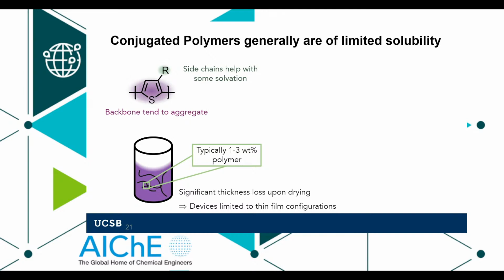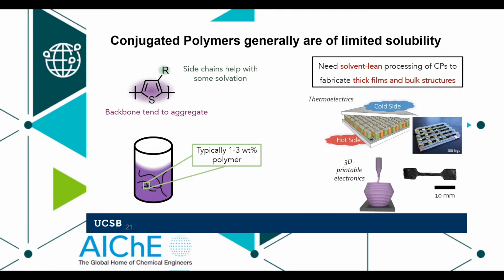And as I said, this is a problem across anything you could think about with conjugated polymers. The backbone is rigid, it tends to aggregate, it's not soluble. We all add side chains to try and help with the solvation, but typically you only get 1 to 3% solubility anyway. And that makes it very, very hard to make any kind of device that's not just a very thin film. And that was a problem when we were working on thermoelectrics. It's a problem if you're thinking about 3D printed electronics. We need something that will allow us to do solvent lean processing so we can make thick films, so we can make bulk structures anyway.